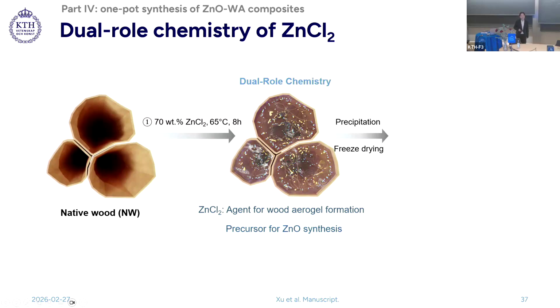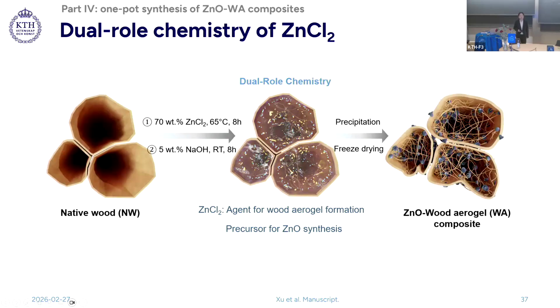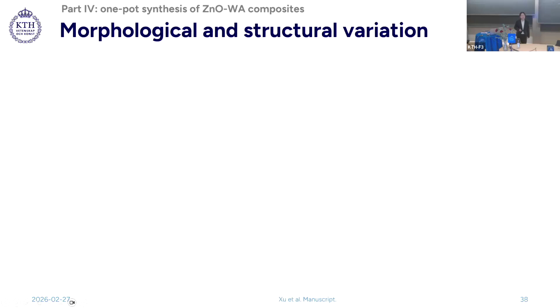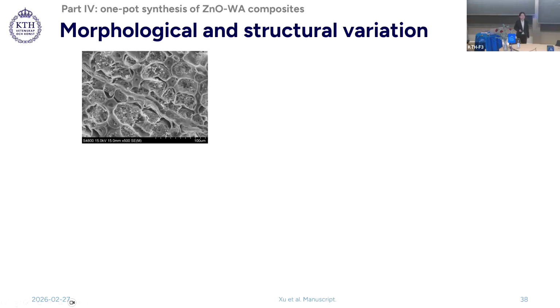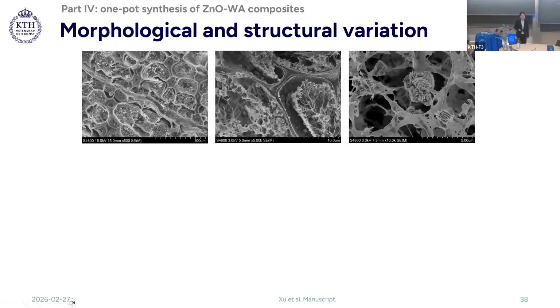The optimal condition was determined to be 70% zinc chloride at 65 degrees Celsius due to its high acidity and its wide use in vulcanized fiber production. The trapped ions here were then converted to zinc oxide by adding sodium hydroxide at room temperature. The obtained composite also shows microfibril networks within the lumen. The flower-shaped particles are distributed throughout the volume by either attaching on the cell wall or intertwining with lumina networks.